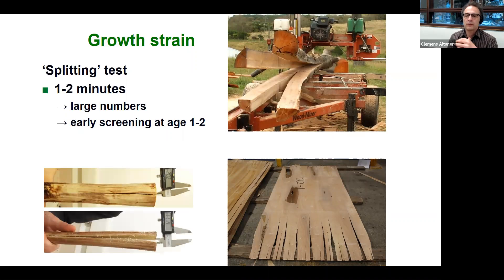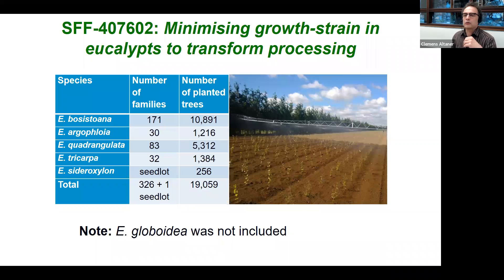The School of Forestry developed a method to measure trees quickly for growth stresses — really measuring the problem, the deformation caused by them. We call it the splitting test. We grow trees for only one or two years to a couple of centimeters thick, then split them along the stem with a bandsaw and measure the opening. A large opening means a bad tree; a small opening means a good tree. We measure the problem directly, very quickly, and can therefore cope with large sample numbers.